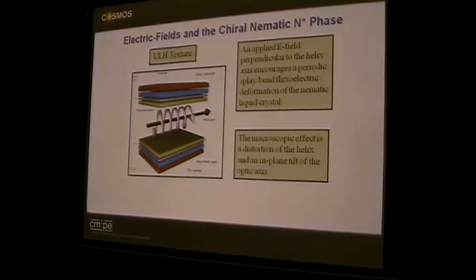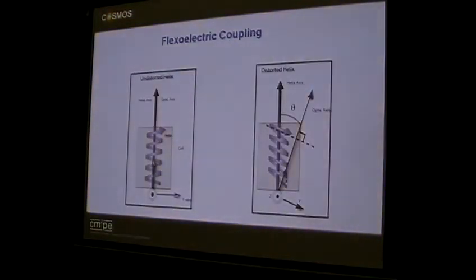Okay. So, using conventional geometry, you apply a voltage across the device and across this spring. In the flexoelectric effect, this spring, if you like, rotates. I'll show you in the next transparency what that means. That means you start off with an undistorted spring here. You're applying a voltage up through the system, so in the direction of the dot there, and the optic axis rotates through an angle theta. So you have a birefringent material that is rotating in space.